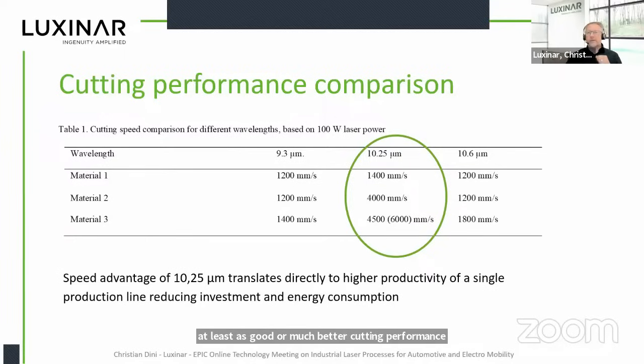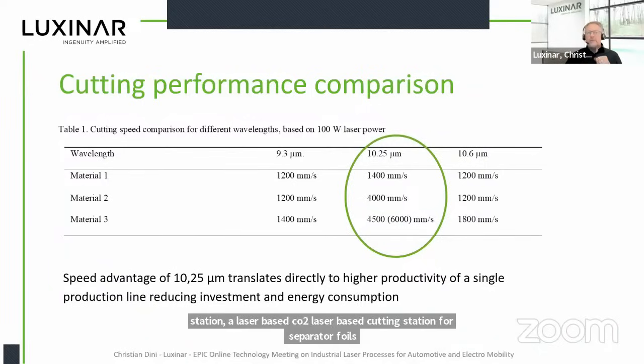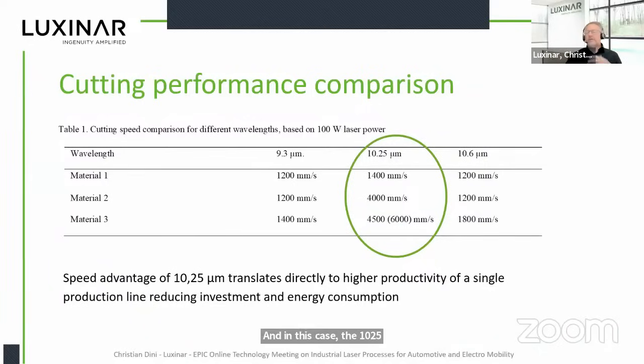So this is something I recommend everybody look into if they are thinking about coming up with a cutting station, a CO2 laser-based cutting station for separator foils. And in this case, the 10.25 really translates into not only higher productivity, but you basically get up to 3 times, actually even 4 times depending on the material, out of the same production line if the laser would have been the bottleneck before, if you used 10.6 or 9.3.